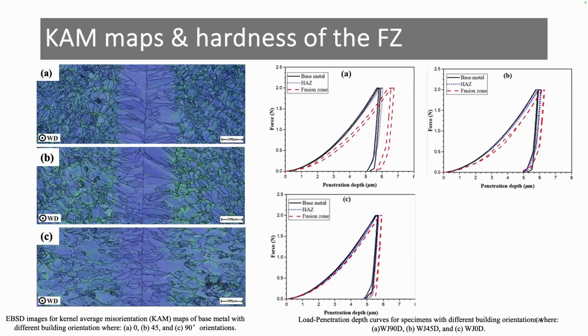And here the KAM results. Also, you will find that the fusion zone has less misorientation than the base metal. It means that the 1000 degrees Celsius heat treatment was not sufficient for the stress relief after laser powder bed fusion. And for the penetration, for the hardness value, you can find that the penetration depth is increasing at this 90 degree, while here the difference between the penetration depths between the fusion zone and base metal is nearly the same.